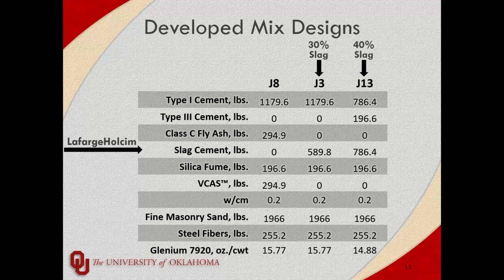It's sort of something similar to slag cement, which is much more expensive. And then J3 and J13 were the two we picked, and they actually had the most slag cement. So one thing we found when we started using slag cement in our mixes was that we were able to reduce the amount of silica fume we use. If you notice, our silica fume is actually really low. I think it's about 10% of the cementitious is silica fume, which is lower than typical UHPC mixes. And we replaced it more or less with slag cement.